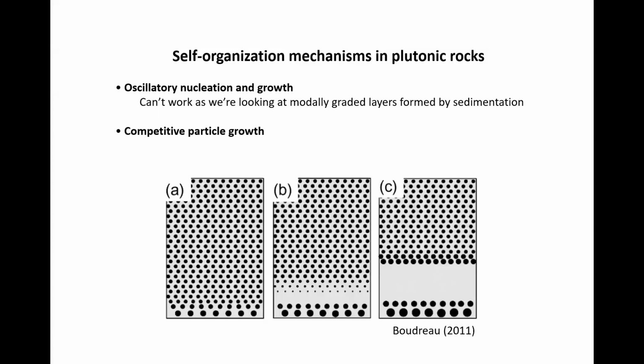So I just stole this diagram from one of Alan's papers. In order to get competitive particle growth, what you need is a grain size gradient. It's driven by the fact that larger grains are more stable than small grains. So when you've got a grain size gradient like this, those large grains here see smaller grains there. This is just like school playground bullies, right? They start dissolving them and eat them up and they become bigger. And then you're left with a layer without any particles.